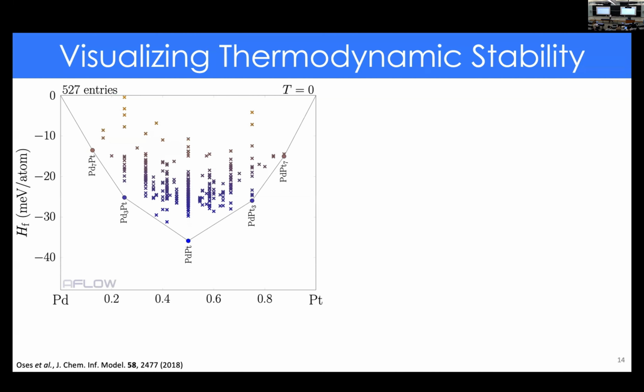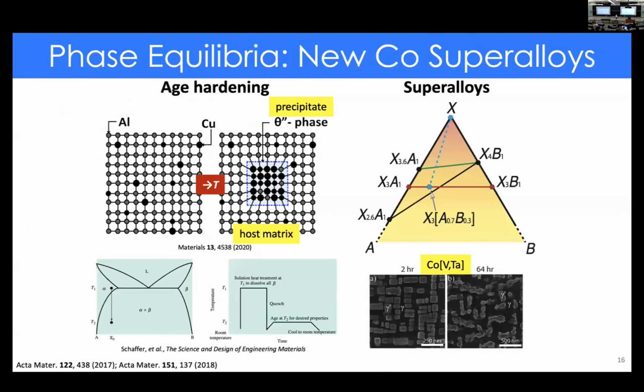The bridge here is that if we try to mix these two components in the lab, let's do the 50-50, we expect that it's going to form this system. And that's what the calculations are telling us. Then we need to see, do those calculations match experiment? Here we have a facet which shows us that we have two-phase equilibrium. Basically, it says that if we try to mix something in the middle here, it's going to phase separate into these two components. They happily coexist like oil and vinegar.